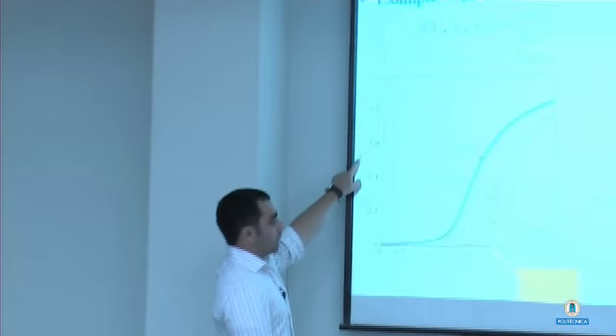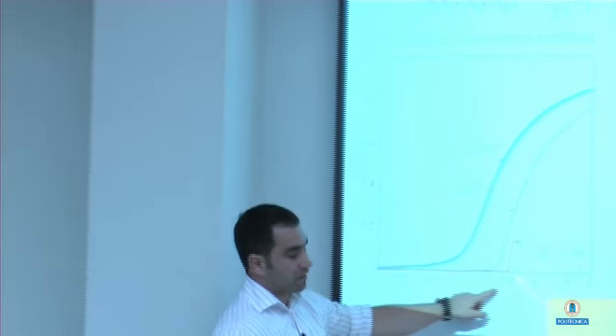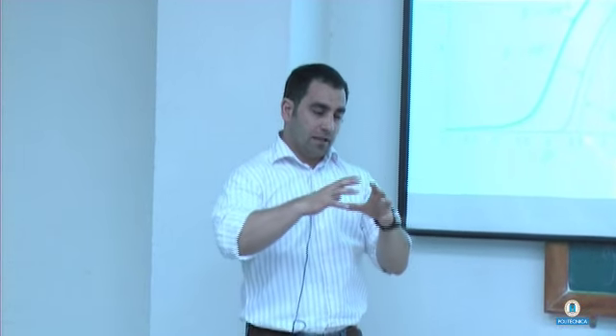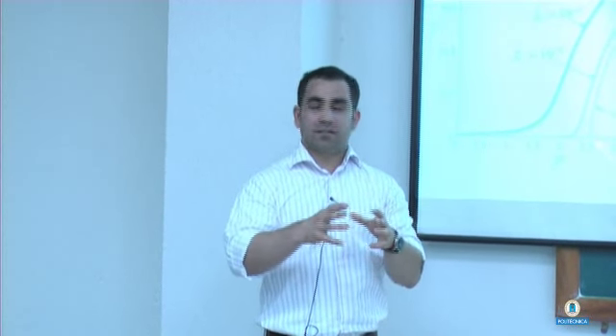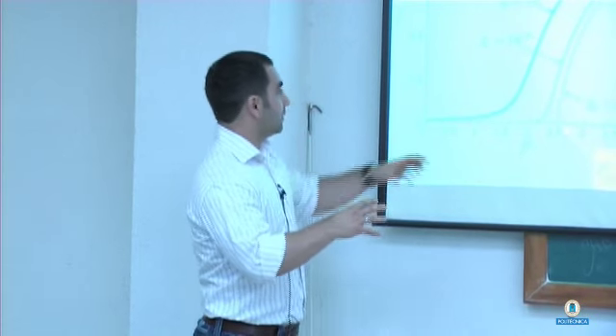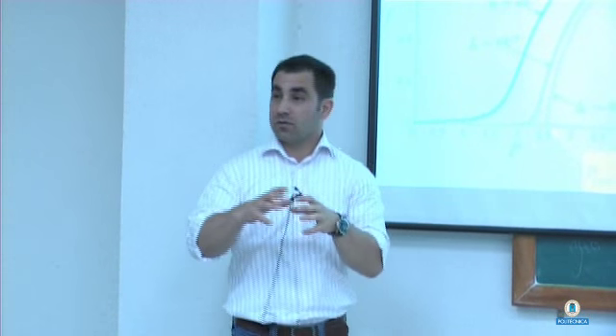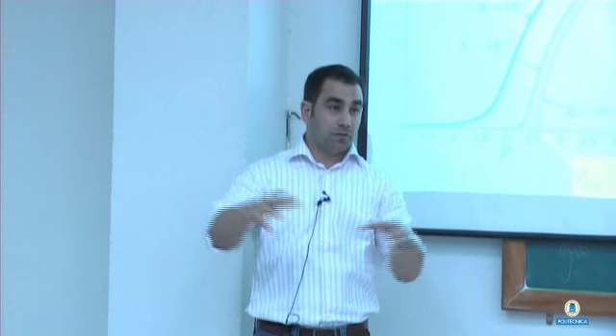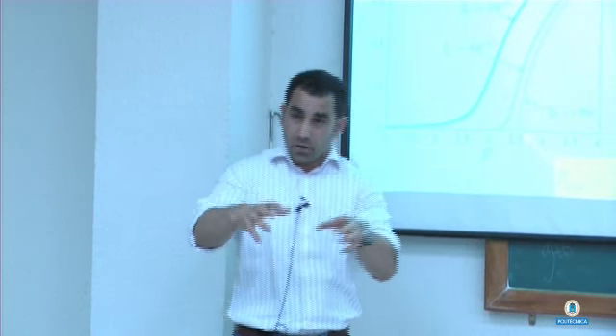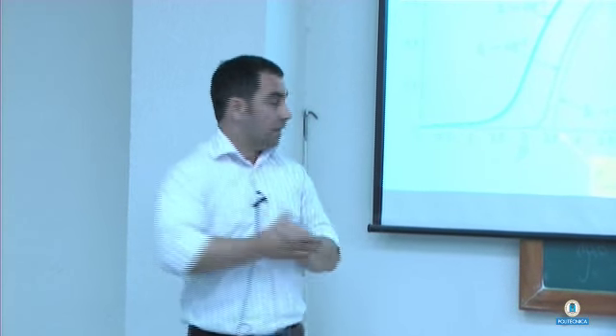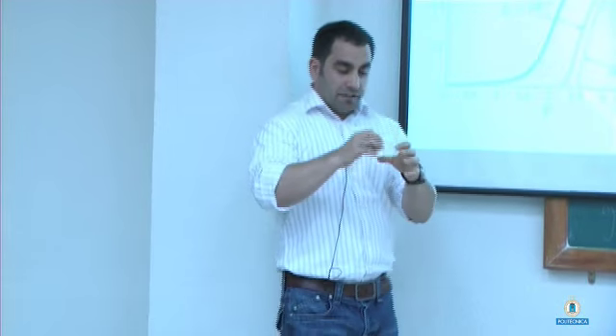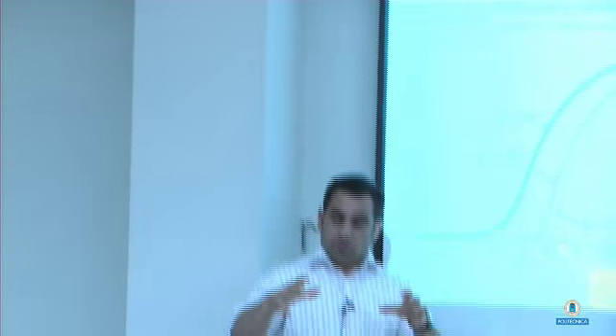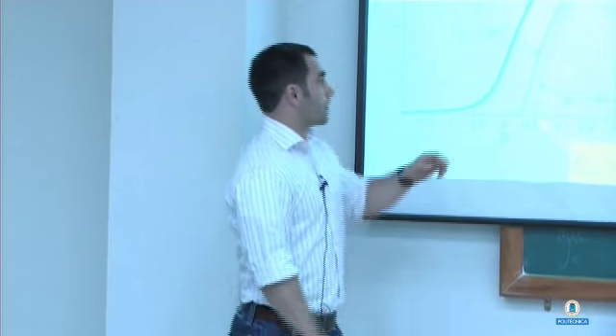Now this is a plot of current porosity as a function of the applied pressure, right? Now, the material is incompressible, and you're applying hydrostatic loading, right? So therefore, if F naught goes to 0, this thing is going to be rigid, right? If it's incompressible, it doesn't want to deform, because the deformation that you want to impose is changing volume, right? So the only thing that can happen is the hole grows. The deformation that you apply on the boundary has to go directly to the hole.